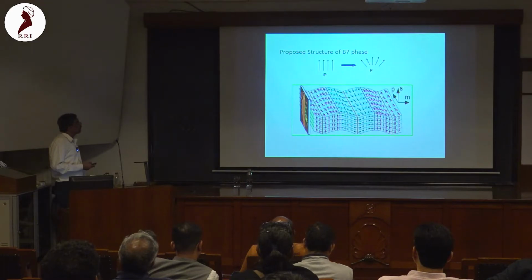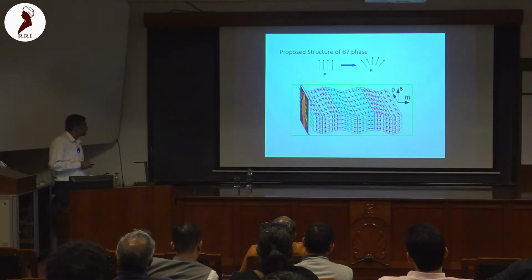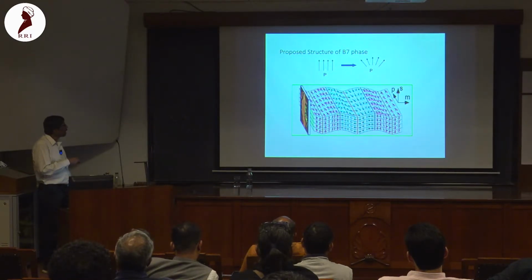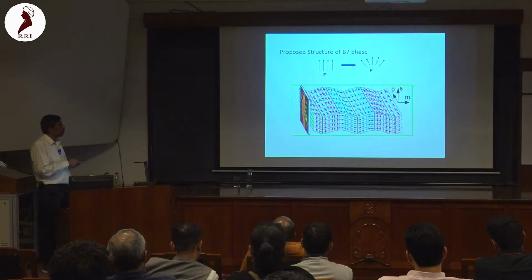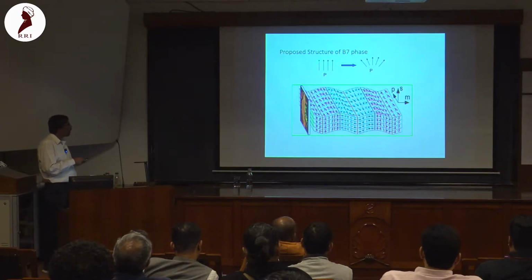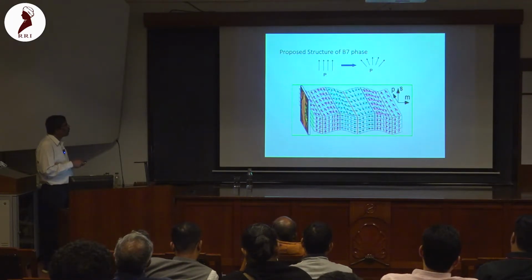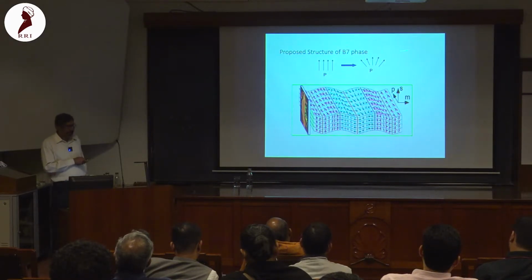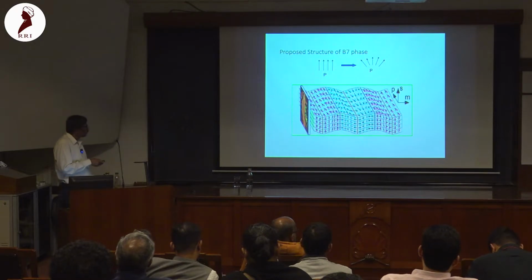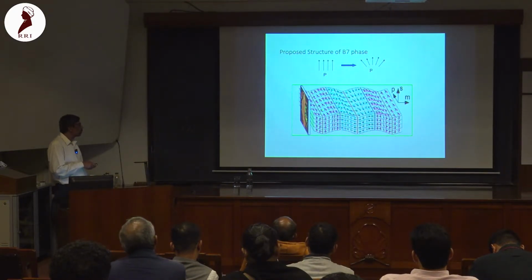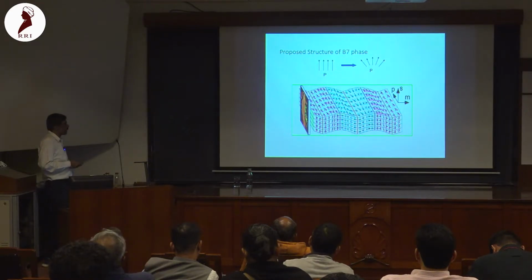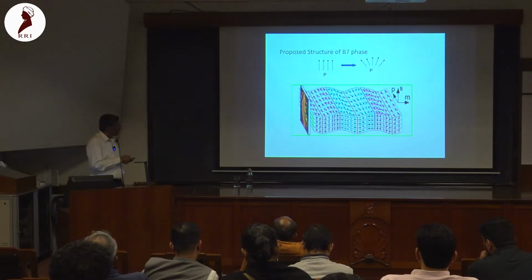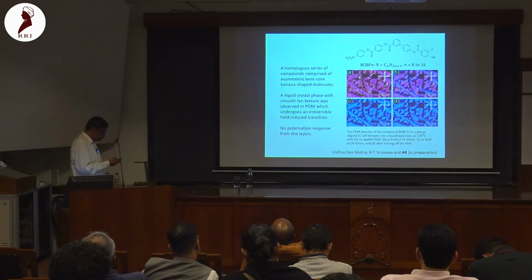So it is found that actually in these layers, there is strong polarization within the medium. And when you try to put the polarization in the layer parallel to each other, we know that this is a higher energy state than this, because the plus ends of the polarization tend to splay and reduce the energy. So this splay of the polarization within the layer gives rise to an undulation in the layer structure. So this was understood to be due to the strong polarization within the layer.